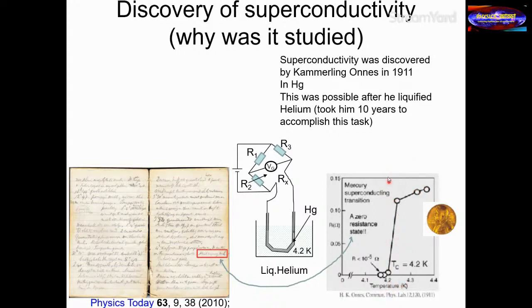The drop in resistance was orders of magnitude. You can see here that the resistance of mercury is about 0.1 ohms, and then at about 4.2 Kelvin, the resistance goes below 10^-5 ohms. So it is a few orders of magnitude drop in resistance. And this was the first time the superconducting state was discovered. Namely, that